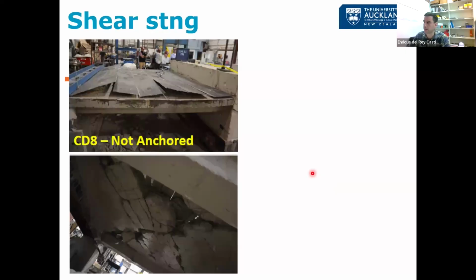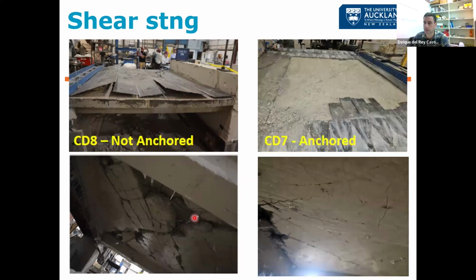But it's very important that the FRP is anchored. For example, we tested, or they tested, I should say, FRP with no anchors, and the FRP just debonds and it does nothing. It's just a piece of plastic on the floor. And the whole slab just breaks down and starts to collapse. And this is the exact same test. It's anchored very well. The floor is perfectly fine. And we have transferred the failure to the shear friction connection between the floor and the wall. The wall is there at a much higher force capacity and with a more ductile failure. This is assuming that the starter bars are properly detailed, of course. If we wanted to strengthen that, it would be a different test.